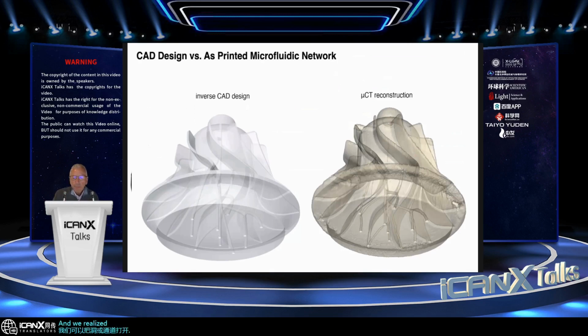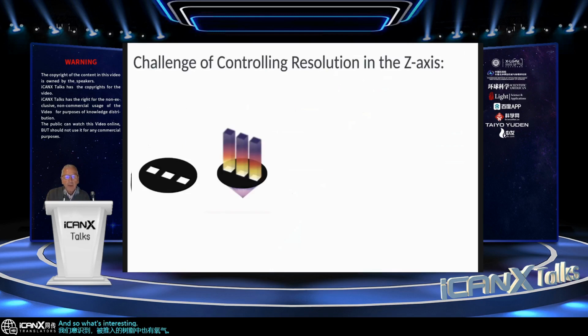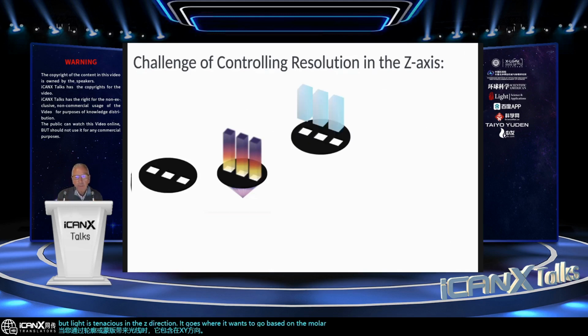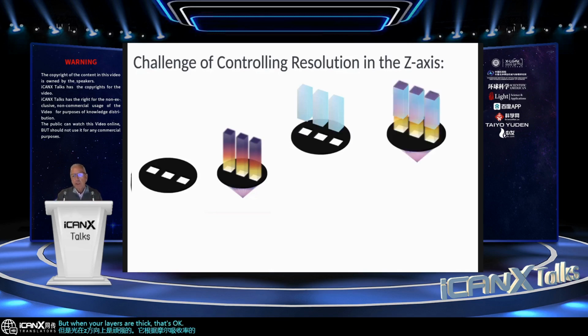And we realized that, well, the resin that's being pushed in also has oxygen in it. And so what's interesting to think about is, back to resolution, when you bring light through a silhouette or a mask, it's contained in the XY direction, but light is tenacious in the Z direction. It goes where it wants to go based on the molar absorptivity of the medium. But when your layers are thick, that's okay. And that's what we do at 75 micron resolution with 50 micron thick layers, for example.